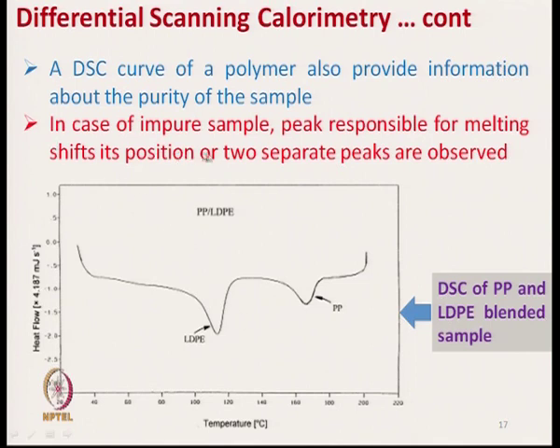So in case of an impure sample, the peaks responsible for melting shift their position, or two separate peaks are observed. Either the peaks may get shifted in case of impure polypropylene or impure polymer, or it can show up two or more different peaks. From there we can come to know whether the polymer is pure or impure.